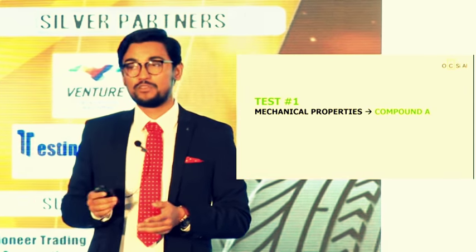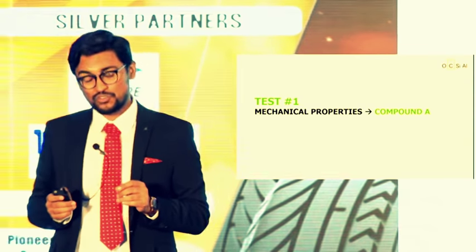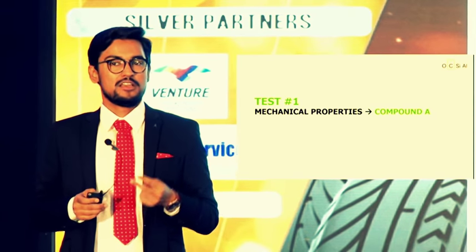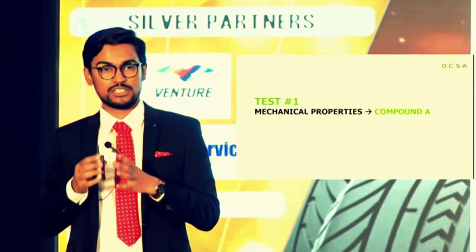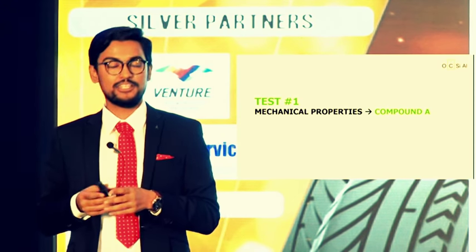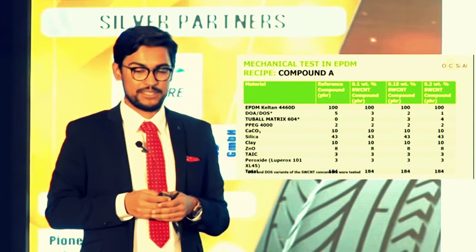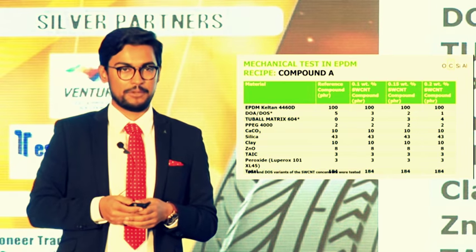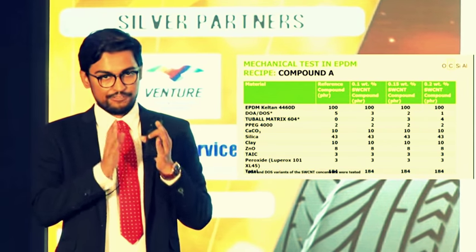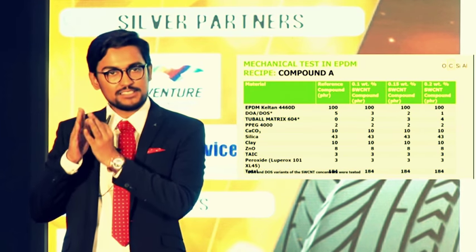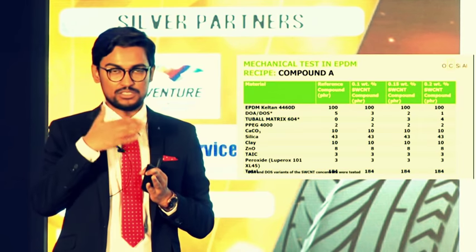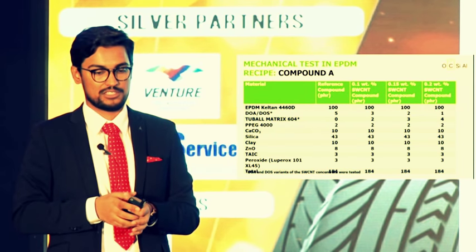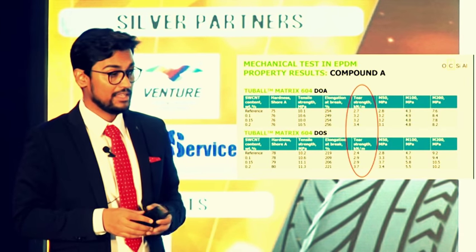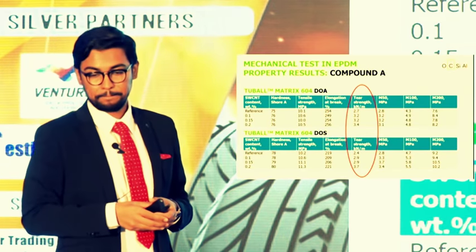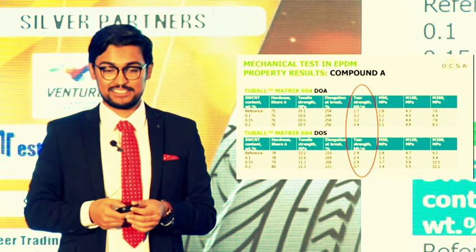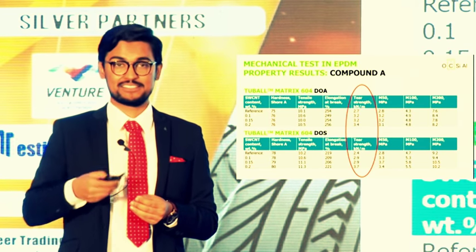In compound A, where we were testing mechanical properties, to take out all the biases which were possible, we used two kinds of matrices. When I say matrix, it is a 10% compound of single-walled carbon nanotube in a carrier. We used DOA and DOS. And these were the recipes used for single-walled carbon nanotube. What we did was, we took a reference compound and we kept on increasing the dosage of single-walled carbon nanotube through this carrier at 0.1, 0.15, and 0.2%, as you can see. And the results were very nice. As you can see, there was a marked increase in tear strength with rapid increase in single-walled carbon nanotube concentration.